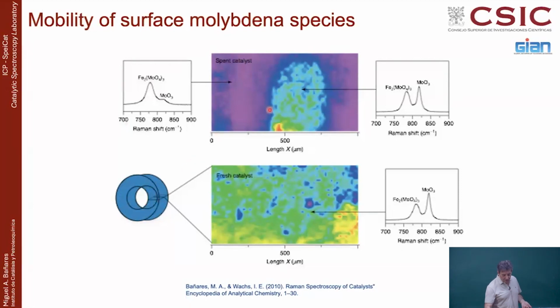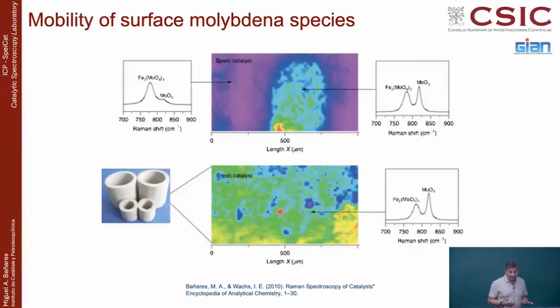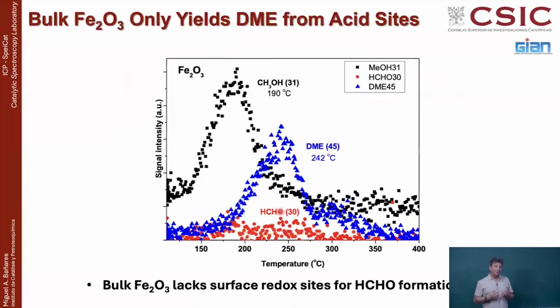And then what you observe is that on the fresh catalyst, you have a distribution where most of it is basically more the Raman band of iron molybdate, and then you got some molybdenum here, but after use, you get a much more even distribution of molybdenum and iron with a higher presence of molybdenum all over the system. So the higher exposure of molybdenum in this kind of catalyst is something important.